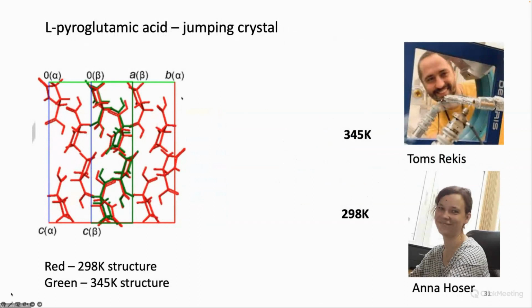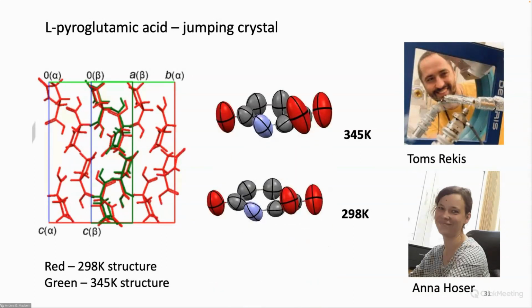So what have we done with this system? We have tried to measure very accurate diffraction data, as good as we could, at several temperatures, and this has been performed by Toms Rekis and Anna Hoser. What we observe generally is that the measurements at high temperature give rise to larger thermal ellipsoids. That is not so surprising, of course. When we heat the system, it's going to have higher thermal displacement parameters.